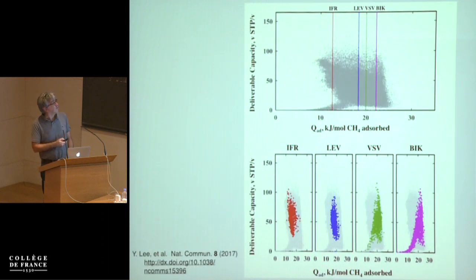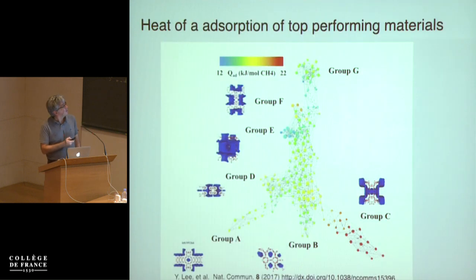So we can make the following graph. We can take representatives of these materials and then look at similar materials, and you see they peak much better now. If you look at it from a physical point of view, you have two things. One is the heat of adsorption, but you also have the entropy of adsorption. And experimentally, they analyzed only a small subset of materials, and those materials happen to have all the same entropy of adsorption. But if the materials are similar, they do have the same entropy of adsorption. So in this way, you naturally separated materials that are similar, but from an entropy point of view.